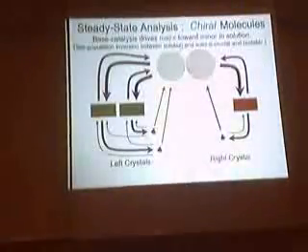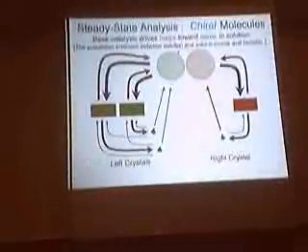And that's testable in principle. Because you have more of one crystal than the other, you measure the concentration in solution, and it should invert in steady state. It may be a very small difference, so that might be hard. But in principle, it's possible. Maybe you could test it by your method, having a little bit more of one than the other. What did you do?